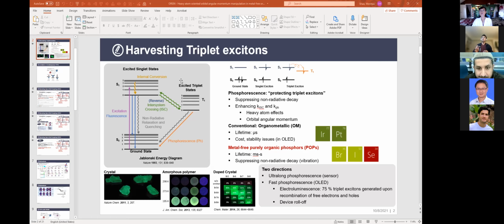You can do that. And in fact, this leads to a more important question: how to do so-called state-specific engineering. People usually consider that when you increase the spin coupling, you increase the spin coupling of everything together. But for upconversion, you intentionally need to shut down the phosphorescence route, so that the T1 to S0 spin coupling needs to be very small, but T1 to S1 needs to be activated and very fast. It is very hard, but we do propose some ways to engineer the material structure, putting in certain functional groups so that it can somewhat realize this goal. But we're not there yet. This is definitely a very important question. Thank you very much.